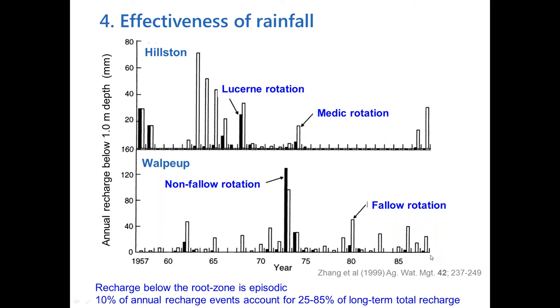And with different rotations, so you've got a lucerne rotation and a medic rotation. The lucerne's in the black square at Hillston. And then they had a rotation without fallow, and they had a rotation with fallow at Walpeup. And you can see, as you'd expect, that with greater water use, you get fewer recharge events. So this is recharge below the root zone.